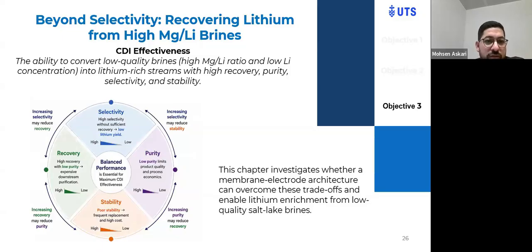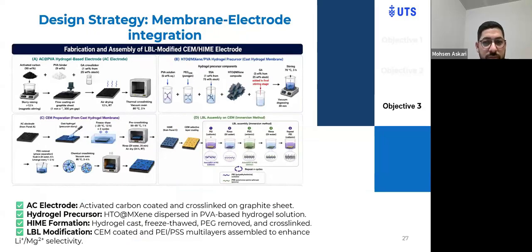Based on our literature review, we found the CDI effectiveness is the ability to convert this low quality brine, meaning low lithium concentration and high magnesium ratio, into a lithium rich stream with high recovery, purity, selectivity, and stability. So the hypothesis in this chapter is to investigate whether a membrane electrode architecture can overcome these trade-offs and enable lithium enrichment from low quality salt lake brines. So we worked on the selectivity, purity, recovery, and stability to make them balanced.